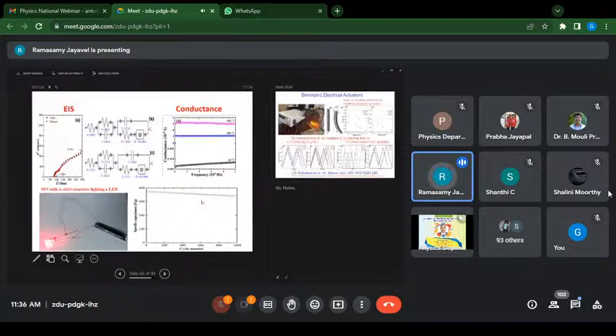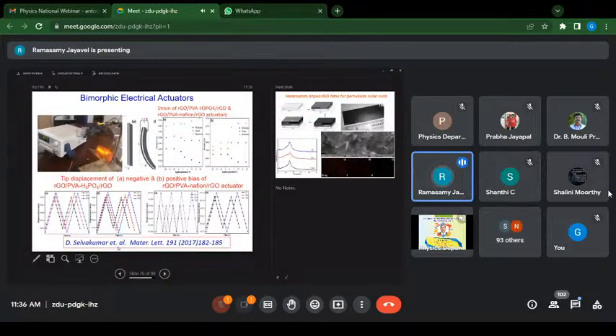So this is actually the graphene sheets separated with the polymer separators, and then connected with the LED to demonstrate the charging and discharging effect. And this is actually a very tiny device we have made with two different polymer separators of this graphene sheet. One is PVA H3PO4, another PVA Nafion, to make the electrical actuators. This is bimorphic because of the double layer, and this is very tiny, and it has got 360-degree flexibility.